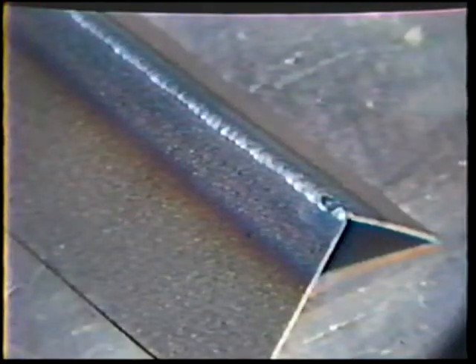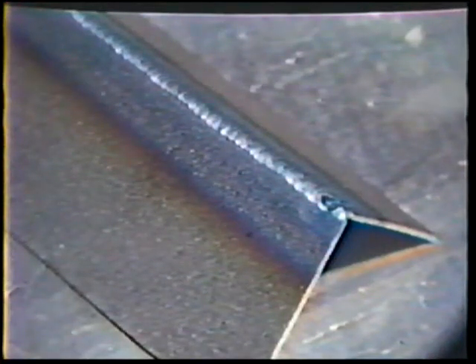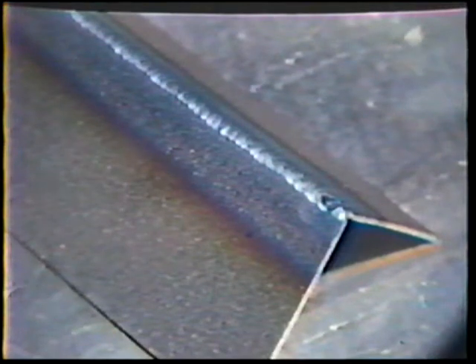The finished weld should be flat and 1 electrode diameter wide. It should also be free of any edge weld undercut. A small bead should be formed on the root side. The next exercise covers the same type of weld, but this time with the addition of 1/16 inch diameter filler metal.